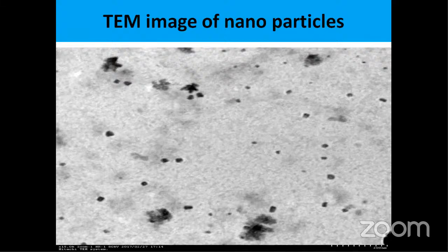Usually the nanoparticles produced without addition of nutrients like nitrogen, phosphorus, potassium were of the size 48 to 50 nanometers. While we had addition of nitrogen, the size was 78 nanometers. Then with phosphorus, it was quite closer to 98 nanometers. However, with potassium, the size was at 52 to 54 nanometers.